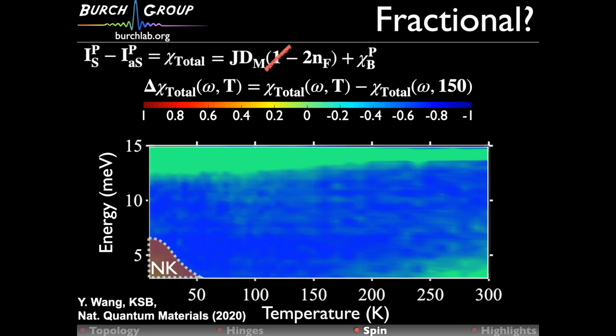Yeah. So if you're looking at the gamma point, this result isn't consistent with the neutron scattering result. People claim you have this sort of star-like excitation. Good question. So actually, they see a continuum at gamma as well, but they only see it above the Néel temperature. And then when they cool below the Néel temperature, that's when they see the magnons.